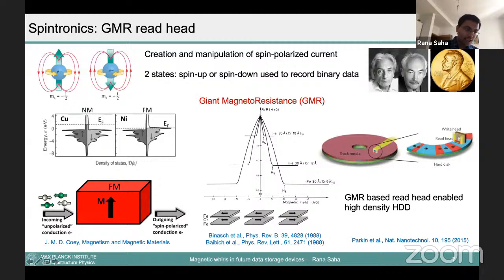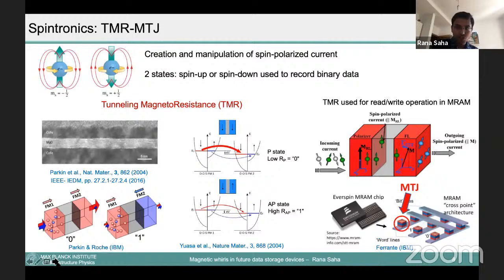So another phenomenon of spintronics: in the previous lecture I mentioned that if you have two magnetic layers separated by a non-magnetic metal, you have a huge change in magnetic resistance. Another memory is also possible if you have two metallic layers separated by a very thin insulating barrier layer. As we know, insulators don't allow electrons to pass through. But if the insulating layer, here shown as MgO, is thin enough, it can happen.